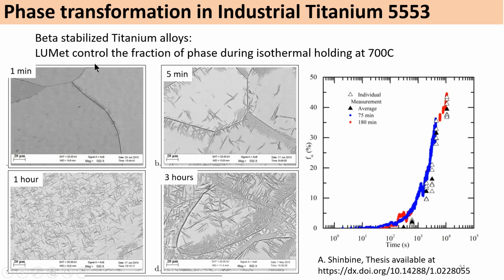But more interesting in titanium is titanium alloys, which are widely used in industry. And so in this alloy, which is alloy 5553, the phase is beta at room temperature, and the hardening of this alloy is obtained by the formation of this alpha needle phase, which starts to grow at the grain boundaries of the beta phase. So as we hold the sample at high temperature, the beta phase will decompose, and the formation of alpha phase will start to occur at grain boundaries.